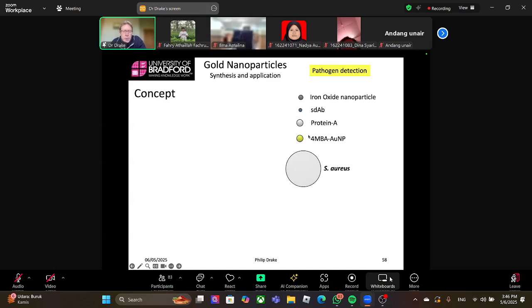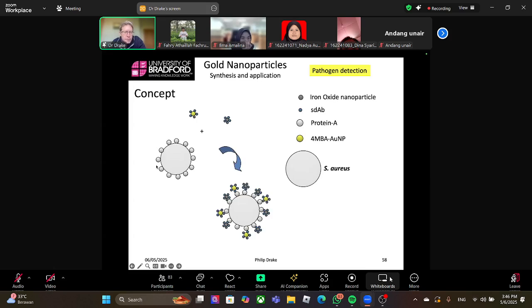We take S. aureus, we take our mercaptobenzoic acid labeled gold, and we also take some iron oxide nanoparticles and some single domain antibodies. S. aureus has protein A on the surface. Our gold nanoparticles labeled with single domain antibodies, and iron oxide particles labeled with single domain antibodies, bind to the surface of S. aureus. So you get gold particles and iron oxide particles on the surface of the bacteria. Now the bacteria is magnetically responsive from the nanoparticles and gives you the strong signal from the gold SERS